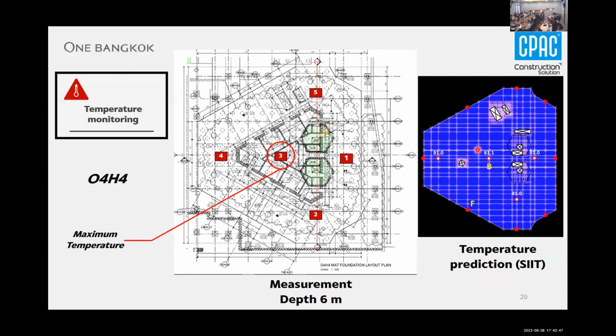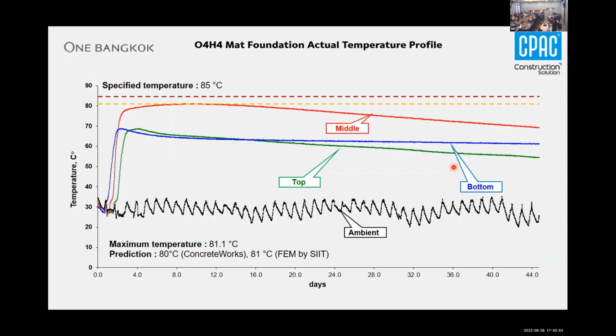And you can see here, we get the number around 81.1. We compare. You can see here the specified maximum temperature, and the red line is the middle temperature that we measured from the real structure. You can see the maximum is around 81.1, and we predicted around 81 from SIIT. We also have our own software to compare the maximum temperature as well. So the prediction and the actual are quite close. That's why everyone is happy about this number. And the differential temperature you can see here is not much.